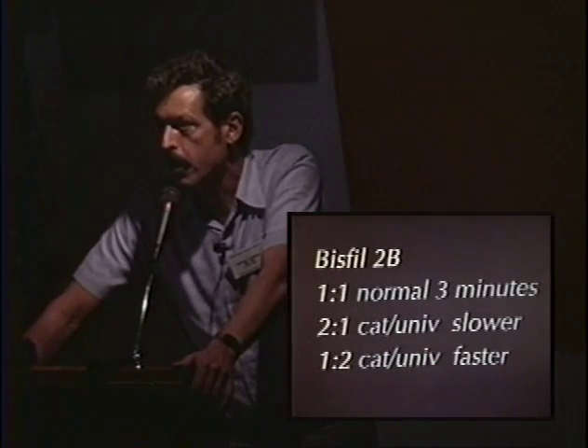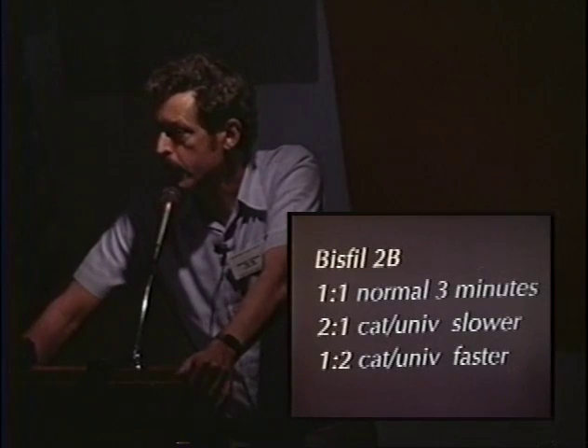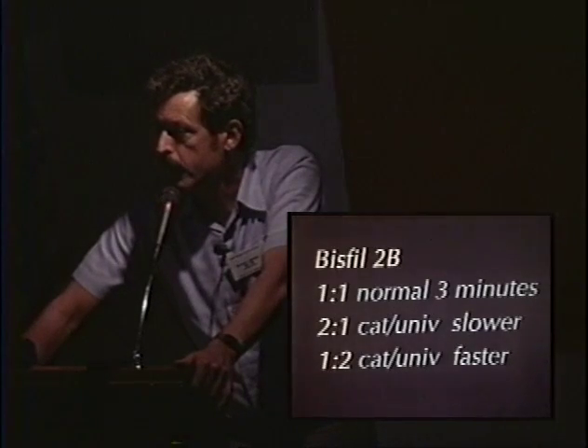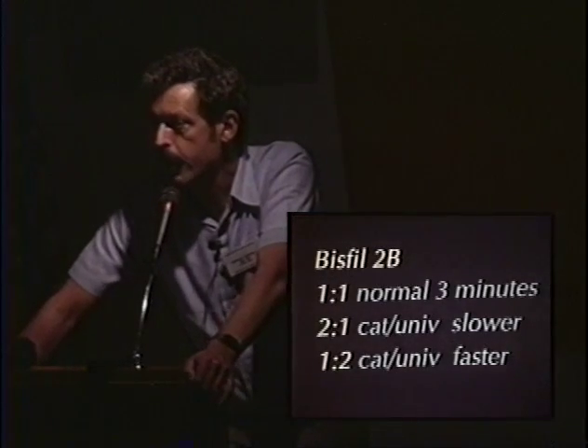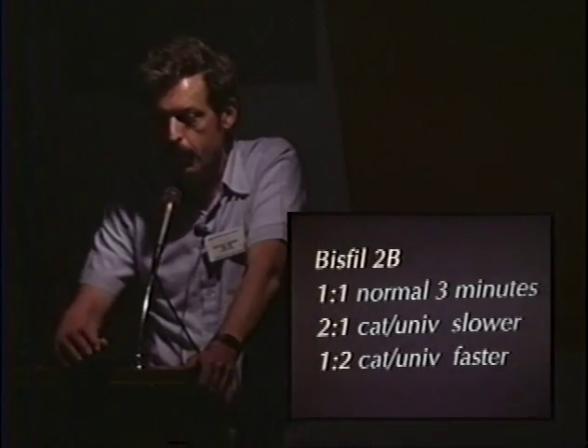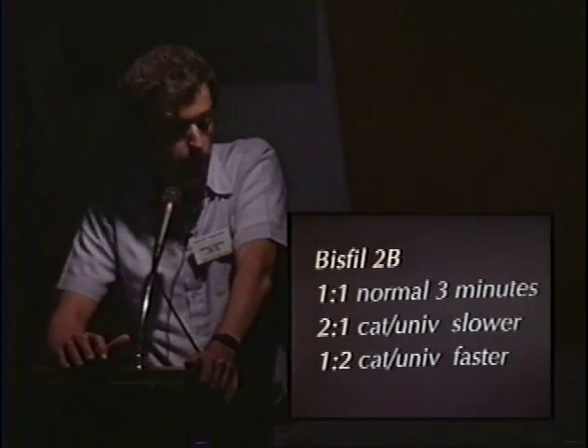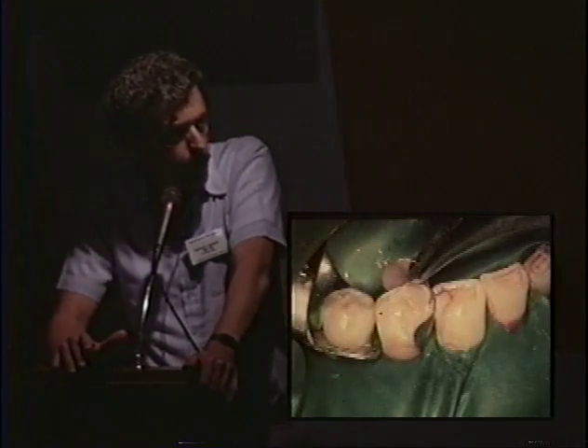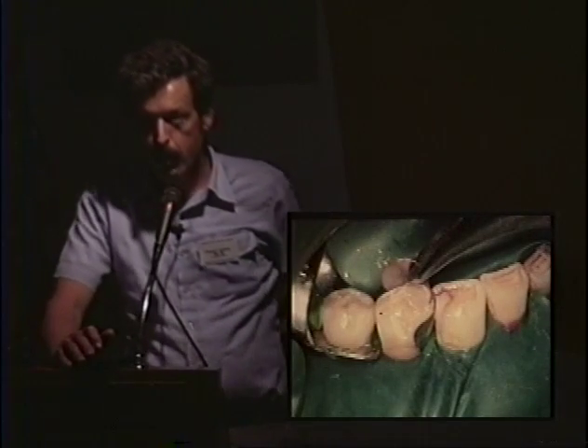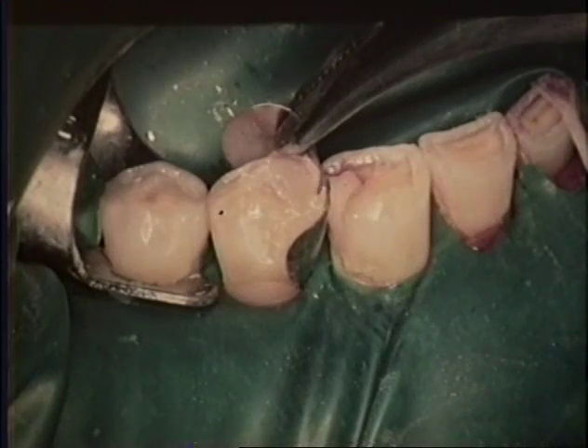The main thing is that the dentin be covered 100% with the auto cure. That's what's so critical. And any margins that are off enamel, of course. Okay, that's really, really critical. Okay, then you take out that matrix band, and first time you do this, it's quite amazing. You think that you can lift that band out very easily with cotton pliers. It didn't come out with the cotton pliers. You need a hemostat at minimum to release the band, because very tight contacts.